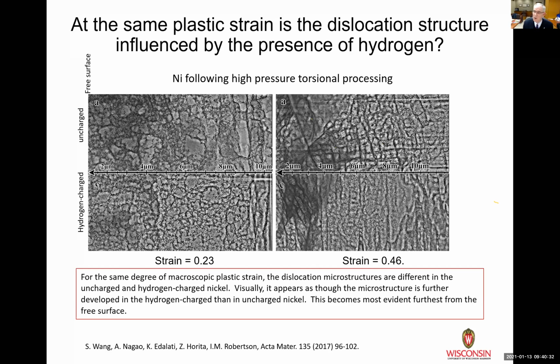If you compare that to the bottom image, one of the things that you'll find is that the cell size is now much smaller. And remember, cell sizes say that the processes have gone further. In the old days, we'd have said that means the material's been subjected to higher plastic strain. They can't be in this case because the experiment was done to yield the same level of a measurable plastic strain. Right? So we've just negated one of the arguments that says these microstructures, the difference, you've taken them at different plastic strains. They aren't. The experiment was designed to give you the same plastic strain, so the microstructures are different.